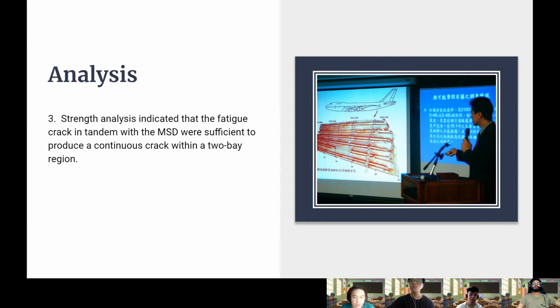Although the ASC could not determine the length of cracking prior to the accident flight, the Council believes that the extent of hoop-wise fretting marks found on the doubler and the regularly spaced marks and deformed cladding found on the fracture surface suggested that a continuous crack of 71 inches in length, which is a crack length considered long enough to cause a structural separation in the fuselage, was present before an in-flight breakup of the aircraft.